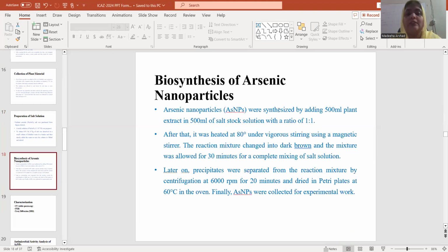Arsenic nanoparticles were synthesized by adding 500 ml plant extract in 500 ml of salt stock solution with a ratio of 1:1. After that, it was heated at 80 degrees centigrade under vigorous stirring using a magnetic stirrer. The reaction mixture changed into dark brown and the mixture was allowed 30 minutes for complete mixing of salt solution. Later on, precipitates were separated from the reaction mixture by centrifugation at 6,000 RPM for 20 minutes and dried in Petri plates at 60 degrees in the oven. Finally, arsenic nanoparticles were collected for experimental work.